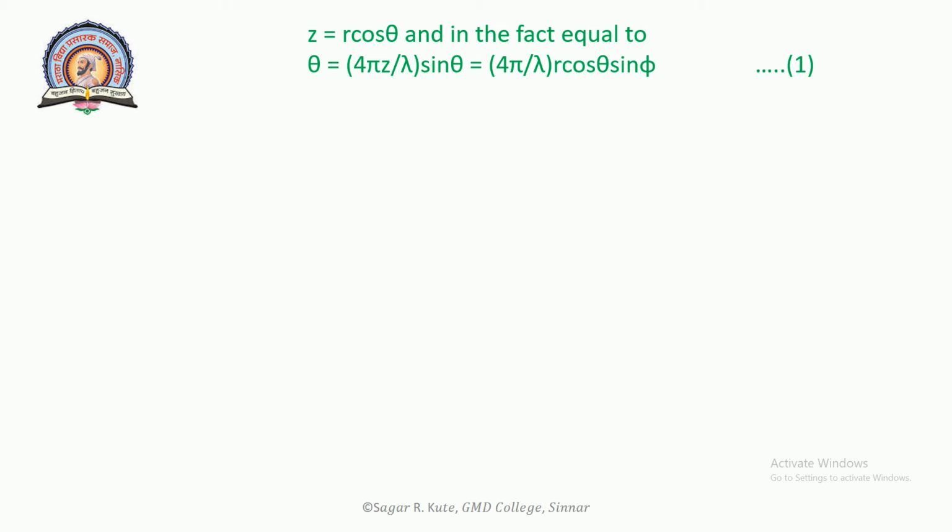On the other hand, the absolute value of the amplitude of the scattered wave is of course independent of the location of the charge and simply proportional to the amount of charge. The ratio of the complex amplitude of the wave scattered by the element under consideration to the amplitude of the wave that would be scattered by the same charge at A is thus simply equal to the atomic scattering form factor.